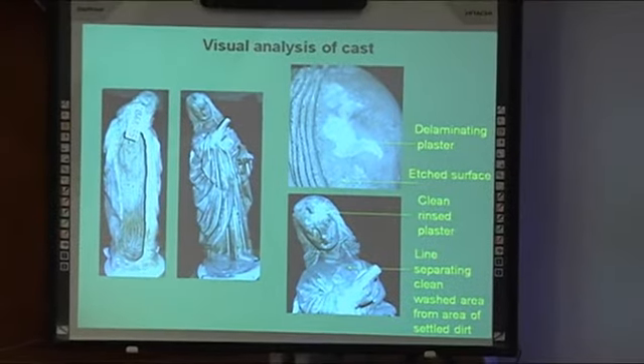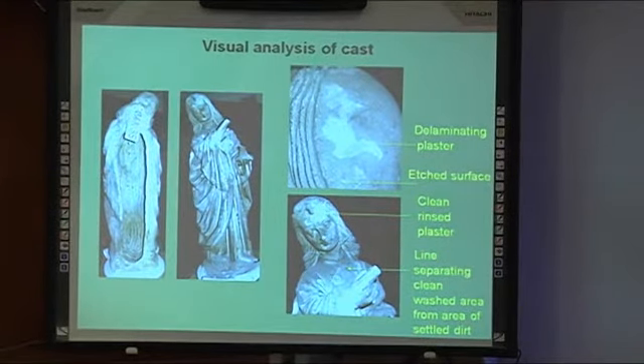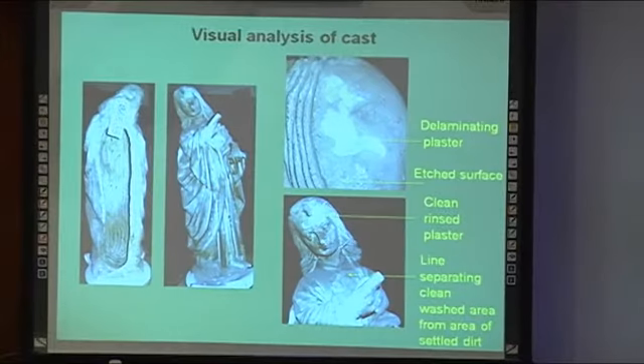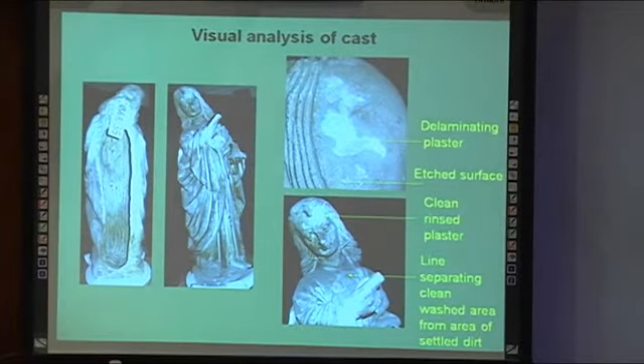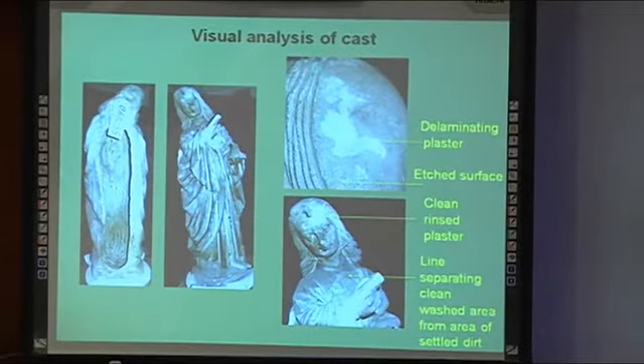A combination of museum dirt and moisture, either from condensation, damp, storage, or even a leaking roof, has altered the surface of the sculpture significantly in areas. Plaster of Paris is soluble in water. This, as well as acidic conditions created by pollution, have etched the surface of the plaster around the shoulders. A clear line following the profile of the head is seen on the chest.